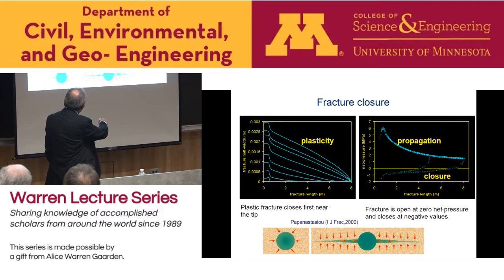And then after the fracture reaches this profile here, 8 meters long, we allow the fracture to close and look at the pattern in which the fracture closes. The theory of elasticity predicts that the fracture closes uniformly across its length and may contact the two faces when the pressure drops to the value of the in situ stresses. And this is the way they calculate the closure stress for calibration, for the big hydraulic fracturing operations after that.